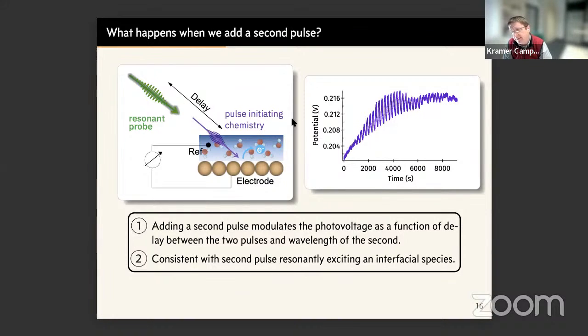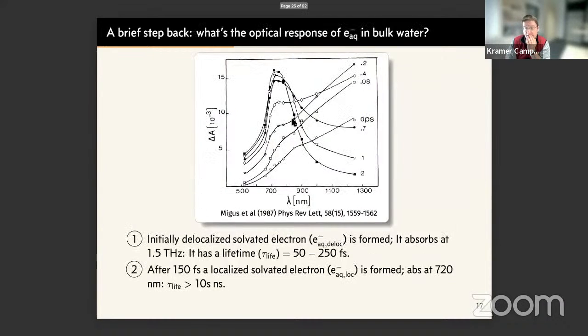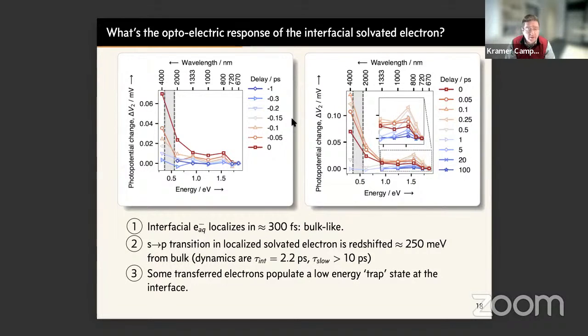And now we've done this experiment, and Francois and Eugene do it at many different time points and vary the photon energy now of this second pulse. And if you do that and extract the amplitudes of this 2-photon photovoltage perturbation, you can create a spectrum. So now on the y-axis is the 2-photon photovoltage change. This is the 2-photon perturbation to this open circuit voltage. The x-axis is the photon energy of this second pulse. So for those of you who like wavelengths, that's the top. For those of you who like energies in eV, that's the bottom.